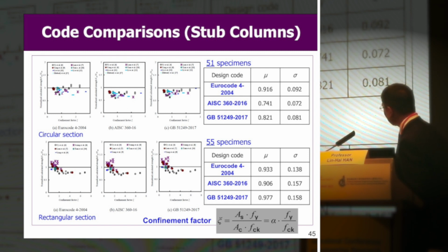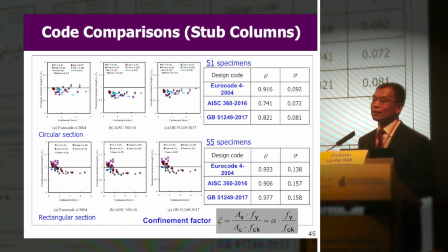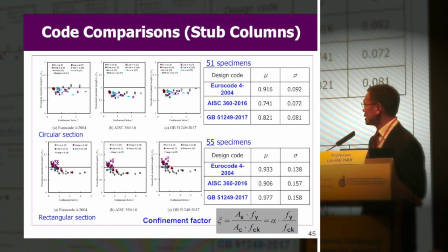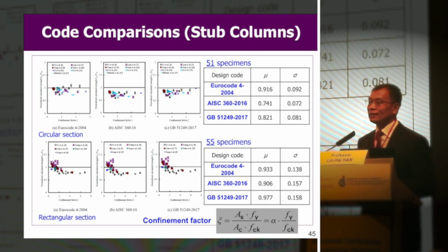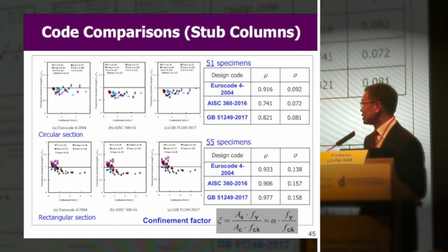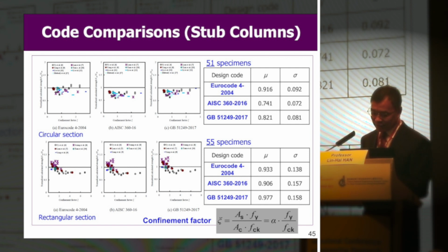Generally, the regulations for the design of concrete filled carbon steel tubular columns give a lower prediction for concrete filled stainless steel tube. But for some cases, particularly for the very small specimen size conditions, the test results give unconservative comparisons. So we are still checking this size effect very carefully in our research group.